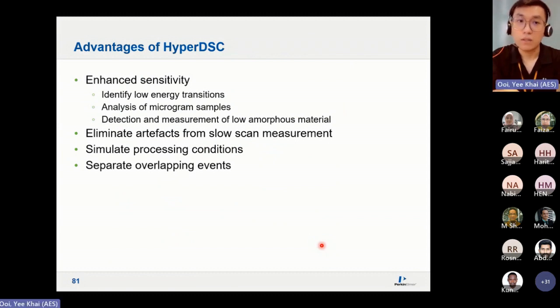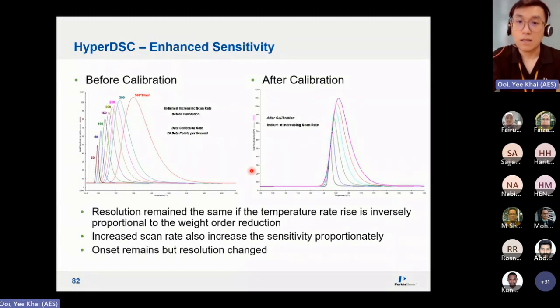So what are the advantages? Enhanced sensitivity, identifying low energy transitions. You can use very, very small samples. And for materials with very low amorphous content, like for the TG, you can use hyper DSC, eliminate artifacts from the slow scan, like the recrystallization that we mentioned just now, simulate processing conditions, and separate overlapping events as well. So this is enhanced sensitivity. You can calibrate at different heating rates. This is important: if you want to use a very fast heating rate, you need to calibrate at that particular heating rate. Like we mentioned just now, W equals joule per second. The faster you go, the bigger the peak will be. So you can apply this concept here.